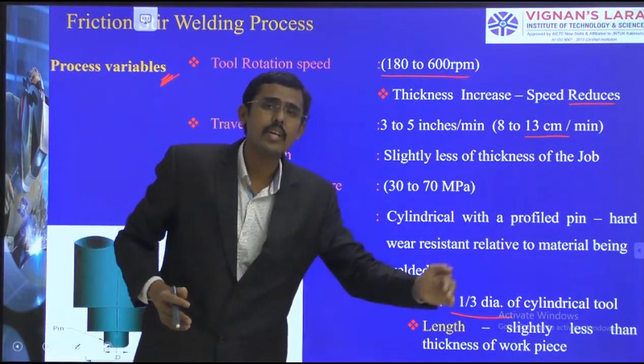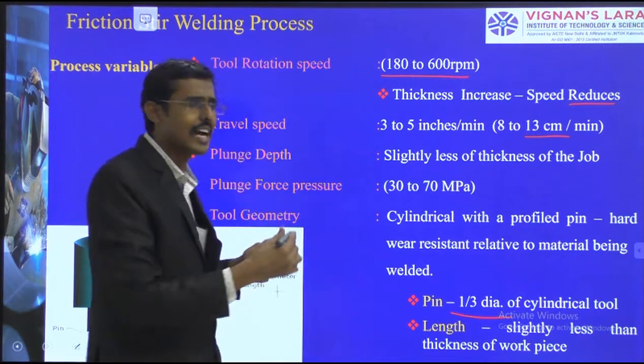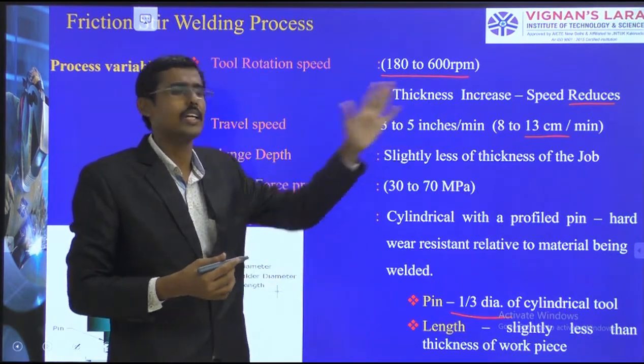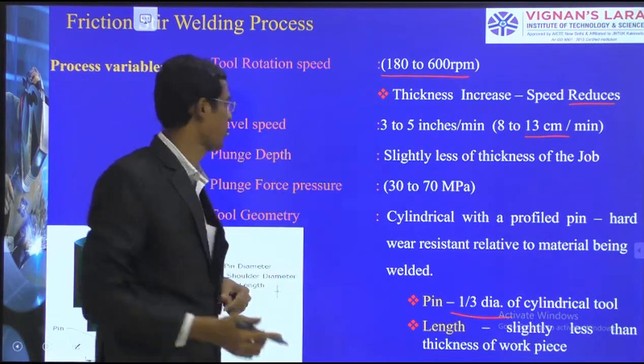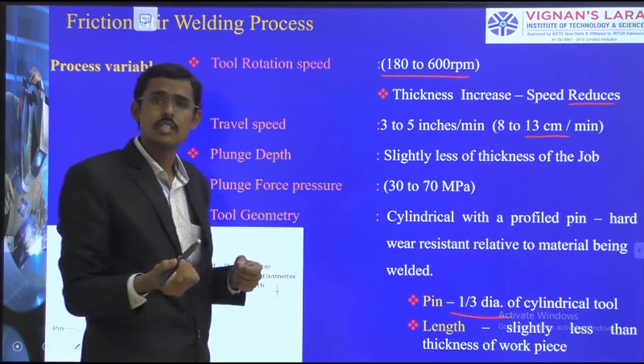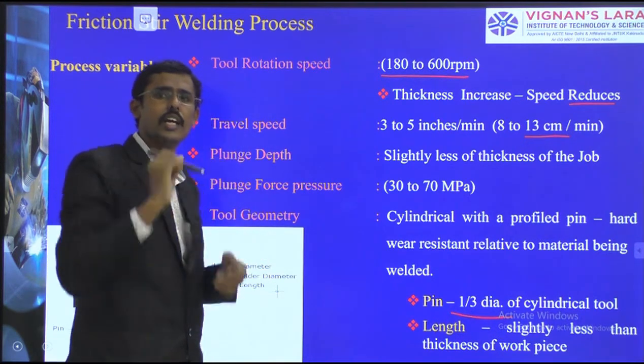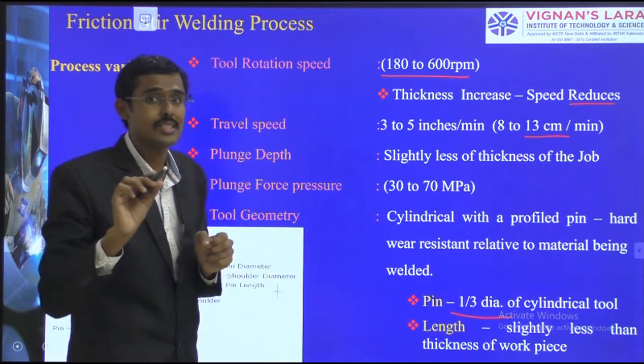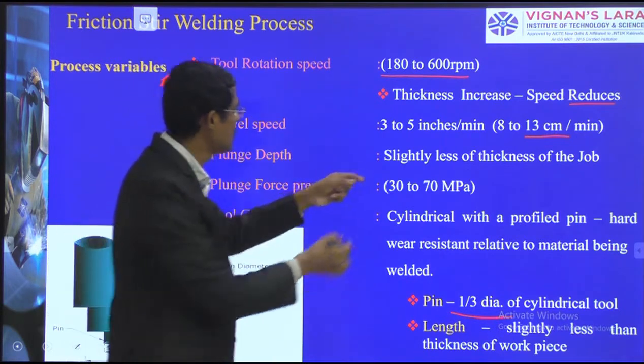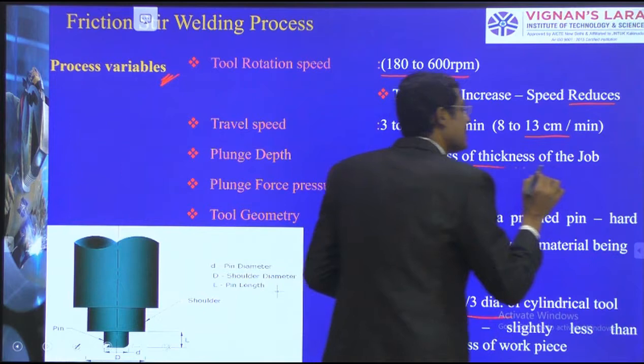13 centimeters per minute we are able to move. So that automatic system approximately it is like that, it may differ. And the plunging depth, how much the pin profile is going inside, we know it is equal to the thickness of the specimen, or otherwise it is slightly less than the thickness of the job.